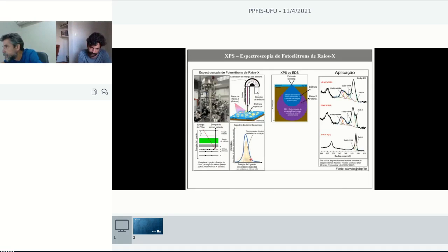And then from the shape of this peak, all the components that you see inside, and here's an example in the right corner, we can judge which kind of oxidation state this atom has, and which kind of species is binding. So it's just oxygen, or it's a hydroxyl group. So this is very powerful information to tell you not only which element you have there, but what's the chemical state of this element. And this technique is pretty much limited to the surface of the material, because different from the conventional energy dispersive spectroscopy, as you see in an electron microscope image, where you excite a large volume, and your signal is based on the characteristic X-ray photons emitted by your atoms,